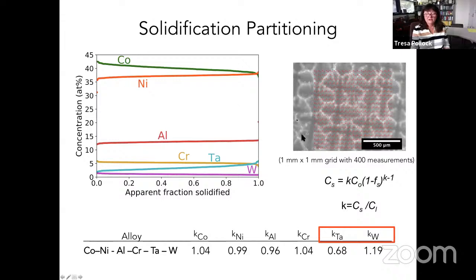And so in these cobalt alloys, unlike nickel alloys, which have strong segregation of basically all of the elements in the alloy, here you can see that many of the elements do not segregate very strongly, with the exception of tantalum. And with this comes a much narrower freezing range for these materials.